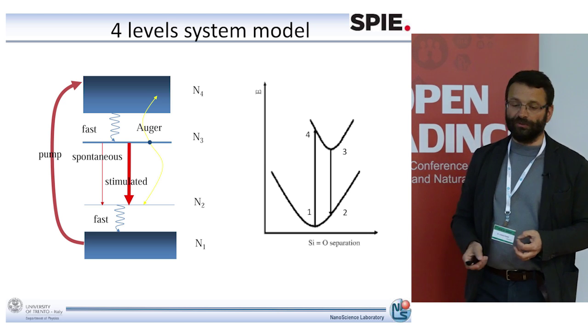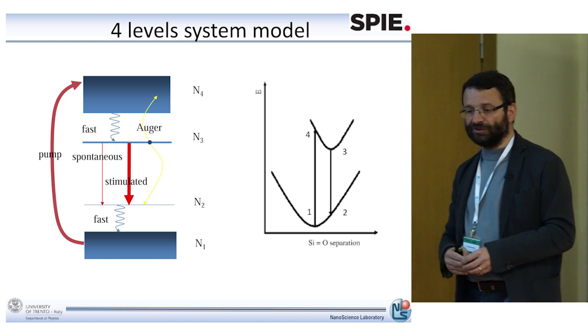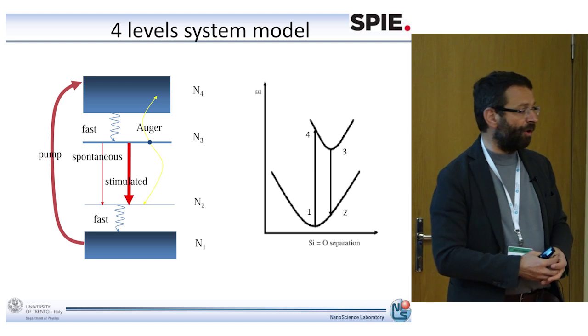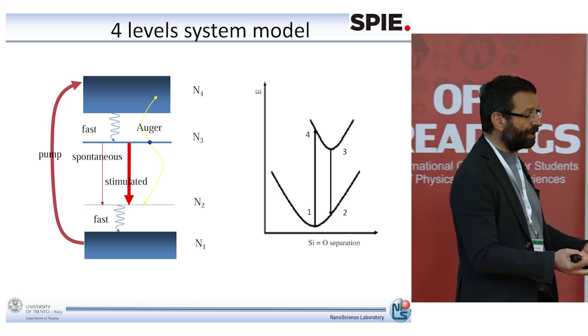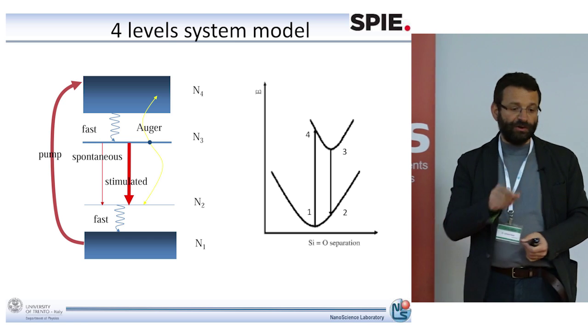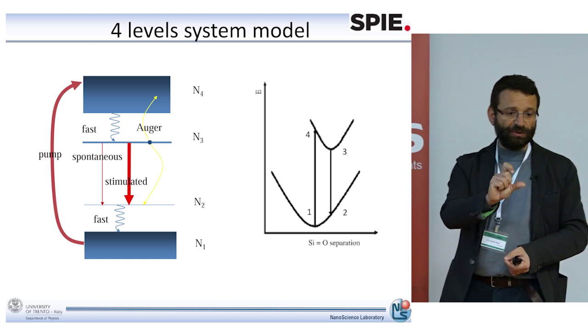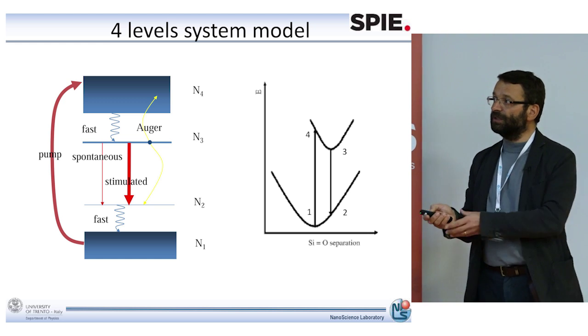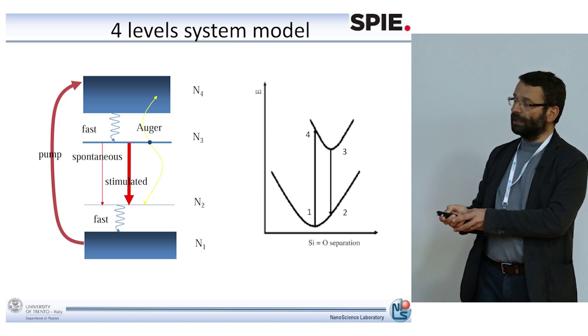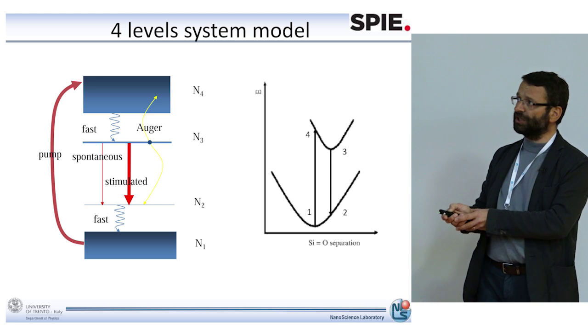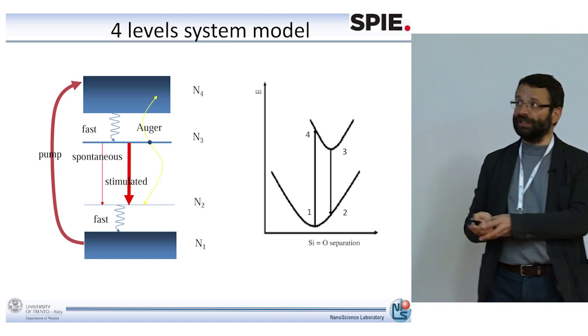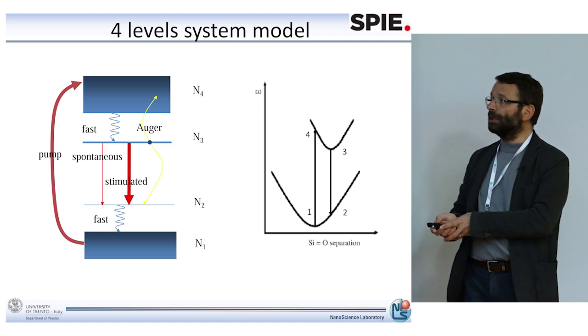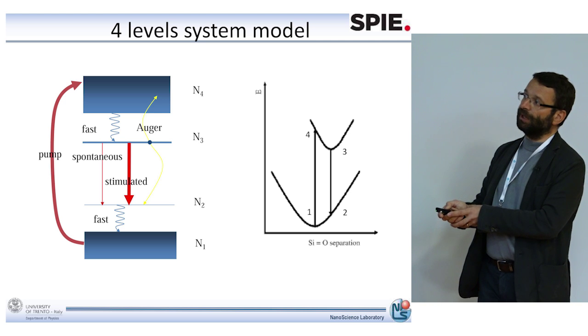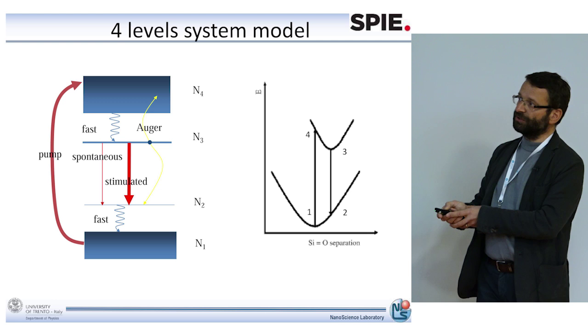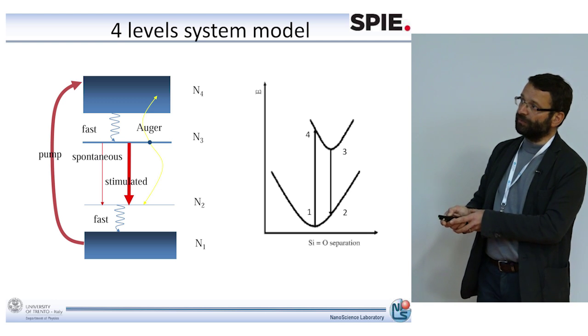And actually what we do observe is that the gain is associated with interface states that form on the interface between the silicon nanocrystal and the silicon oxide within which the nanocrystals are formed. There you form some specific bonds between silicon and oxygen, and what happens is that if these bonds are excited, you get a different separation between silicon and oxygen, and so now you are on these energy levels here. So here, this is the ground state of the silicon oxygen, and here is the excited state of the silicon oxygen interface state. And what you observe is indeed a 4-level system, by which you get excitation from level 1 to 4.